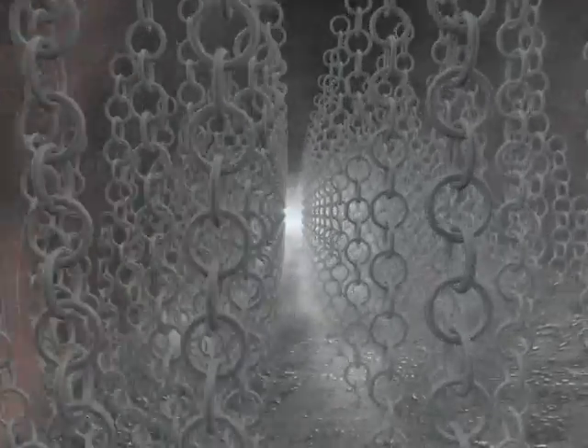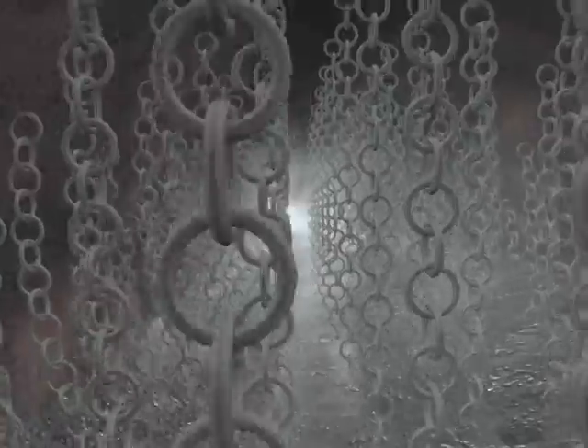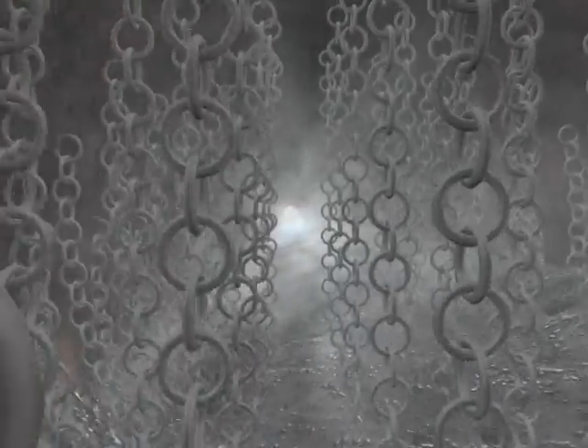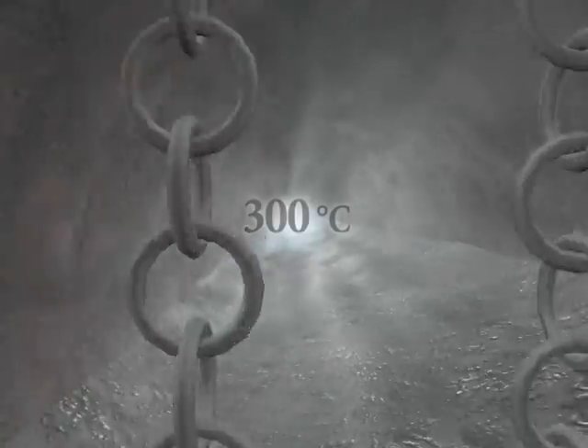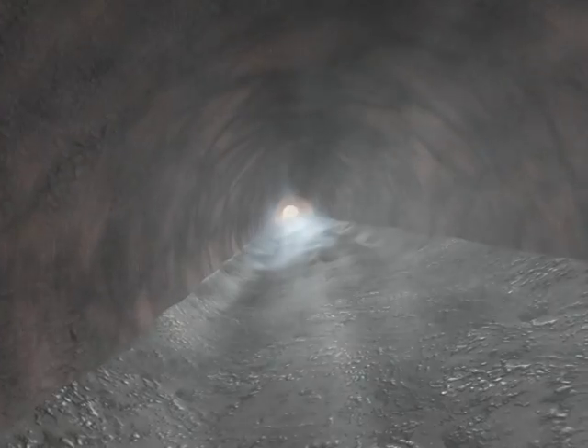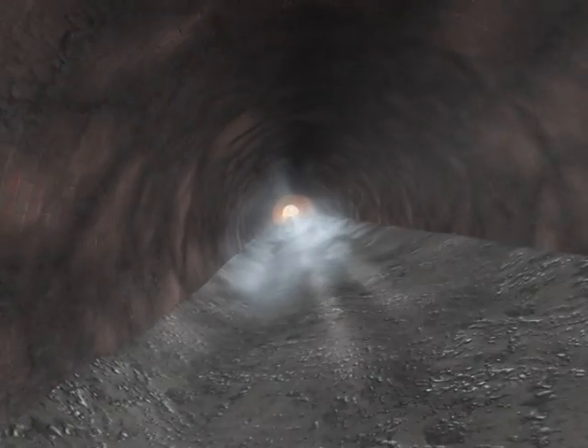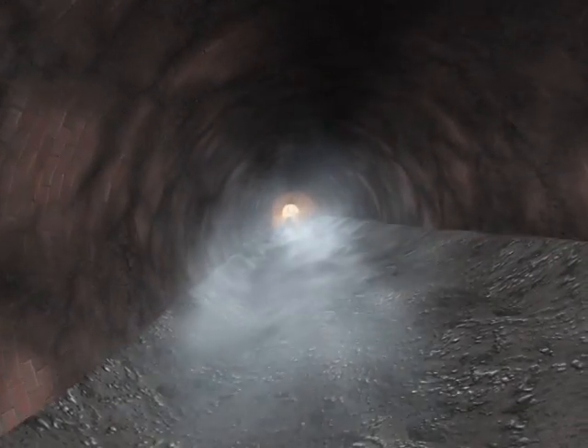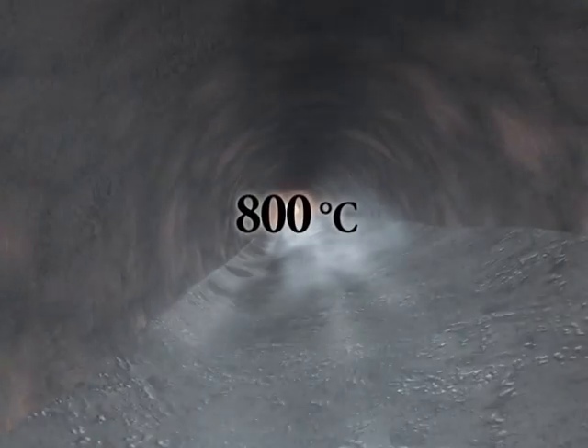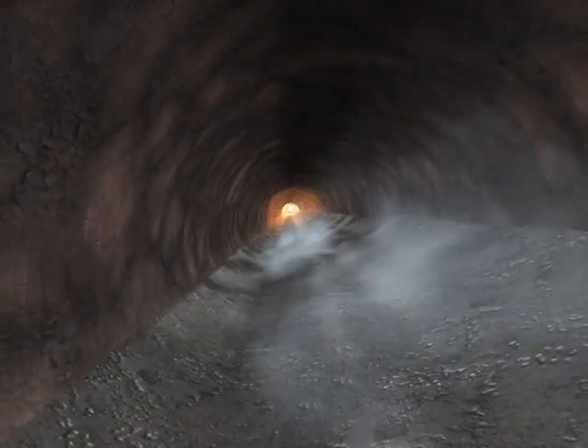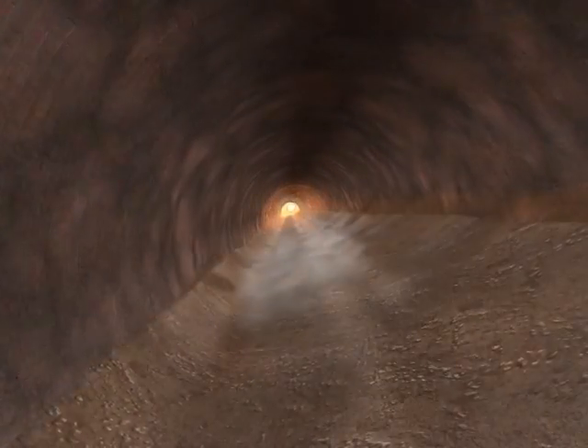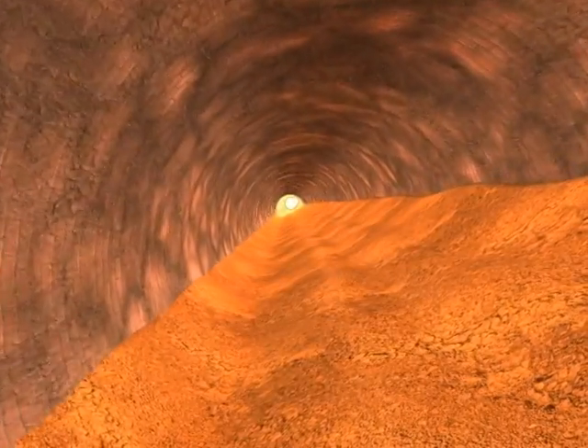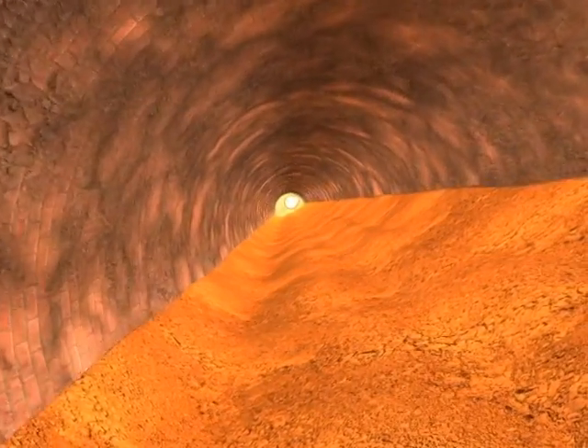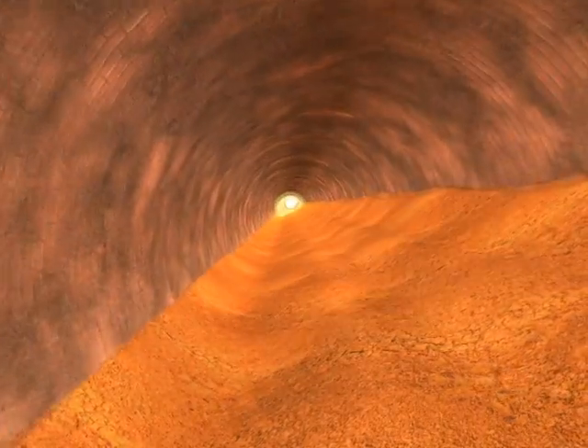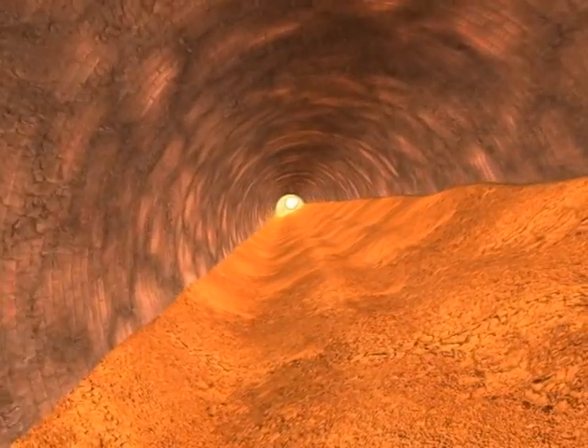The first zone is fitted with hundreds of pieces of hanging chain and is called the chain section. This is where the material reaches its first level of heat at approximately 300 degrees Celsius and where all the water is driven off. The material then travels further into the calcination zone, which reaches a temperature of approximately 800 degrees Celsius and where carbon dioxide is liberated from the feed in a process known as calcining.